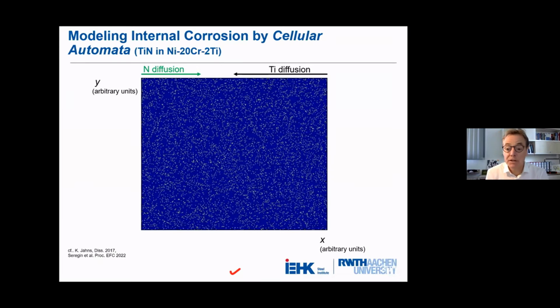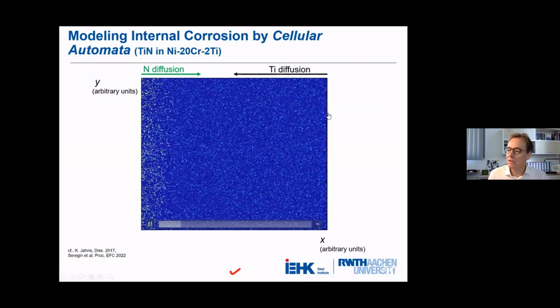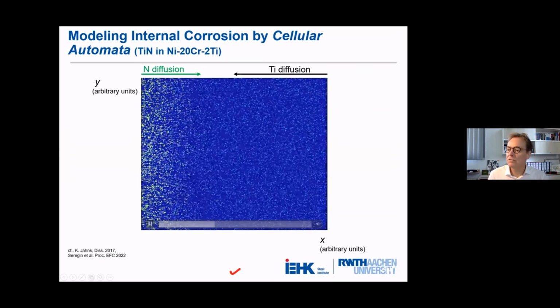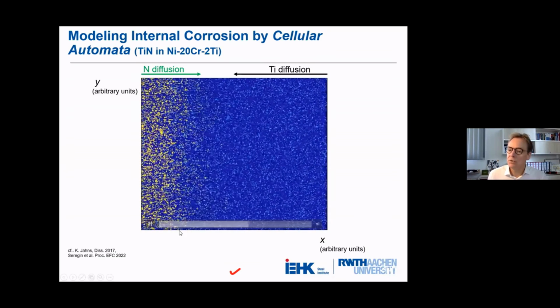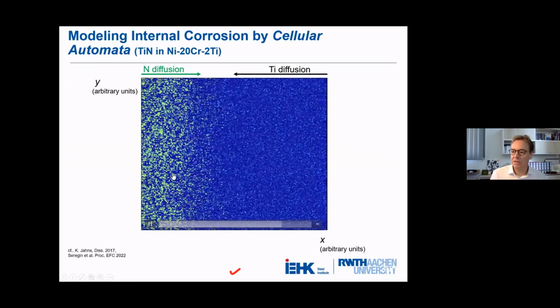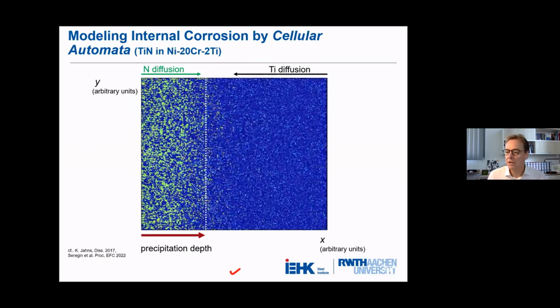More recently, we have been using the method of cellular automata, where we use the probabilities of particle movement in spatial directions, to the top, to the bottom, ballistic or in diffusion direction. By doing this, we can see the diffusion of nitrogen and the counter diffusion of titanium, and here in green yellow you can see the ongoing precipitation, and that allows us to predict the precipitation depth. The advantage of using this is that we can consider the various transport paths and stresses and so on.